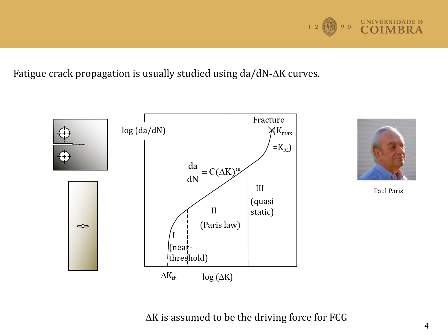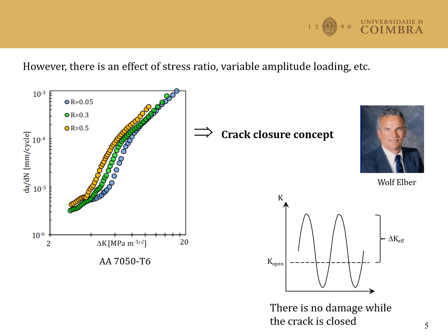However, ΔK is not able to explain the effect of stress ratio or variable amplitude loading. Therefore, the crack closure concept was proposed by Elber. It assumes that there is no damage while the crack is closed. Therefore, an effective ΔK is proposed, which is the difference between K-max and K-open.